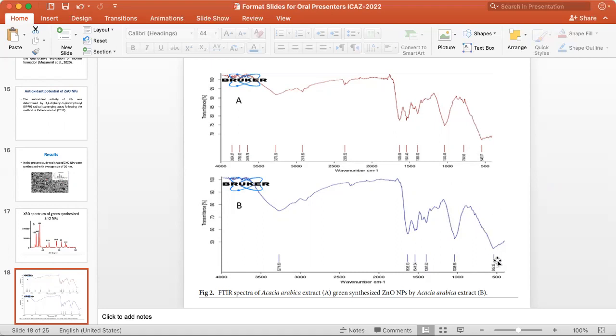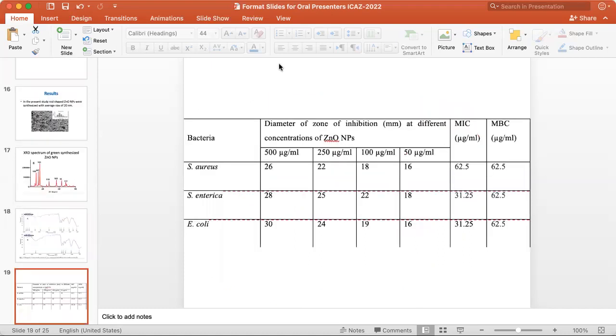Particularly in case of B, you can see here a peak at 545.35 wave number, and this peak belongs to zinc oxide nanoparticles. Whereas another peak that is visible in spectrum A is around 3443, and this peak corresponds to free hydroxyl groups of phenols that were probably used for the capping of nanoparticles.